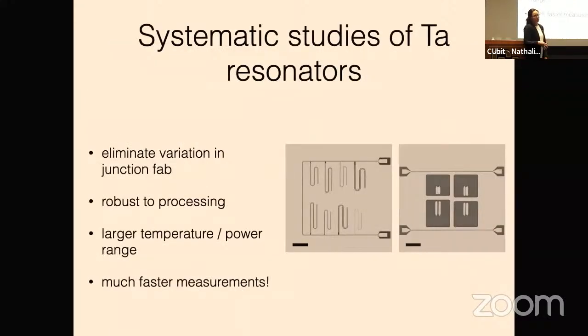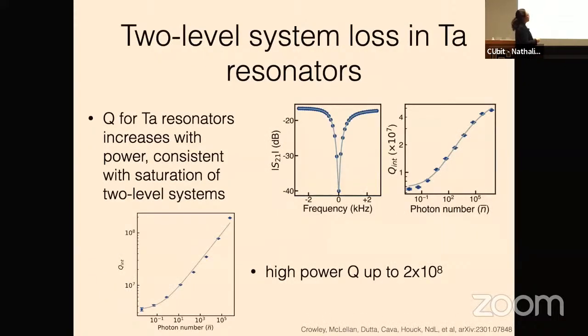Okay, so that was a very exciting result because we were able to push the state of the art of what was possible just with this fairly simple material science. So since then, what we've been doing is systematic studies of what is responsible for the remaining losses in tantalum. So for this, we're making tantalum resonators to sort of eliminate the complications from the Josephson junction fab. And then the idea is that these films are actually quite robust to processing, so we can do a lot of stuff to it and then look at small changes in the losses as we do all of these different types of processing. And then, of course, you have the possibility of doing multiplex measurements because you can put lots and lots of resonators on one feed line and then just look at them in a spectrally selective way. Okay, so, full disclosure, I came into this saying, everyone talks about two-level systems.